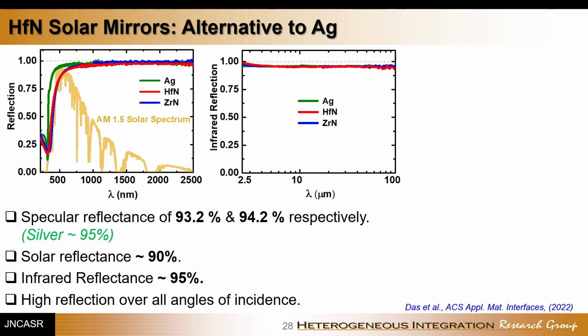And this is shown in this particular case: reflection versus wavelength in the UV to visible spectral range, covering the entire solar spectrum. The green one you see is silver, but hafnium nitride and zirconium nitride are actually operating almost as well. So in terms of numbers, silver has a 95% reflectivity in the visible spectral range, or in the solar spectral range.